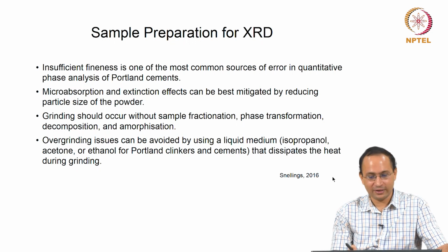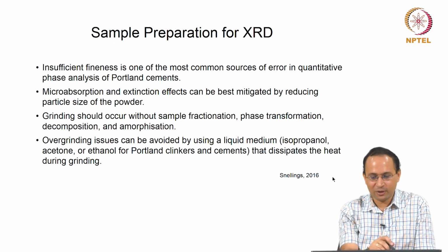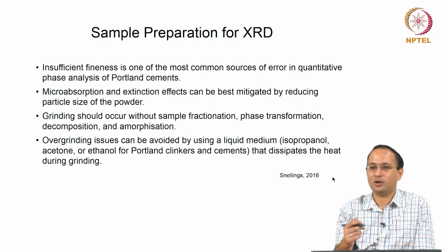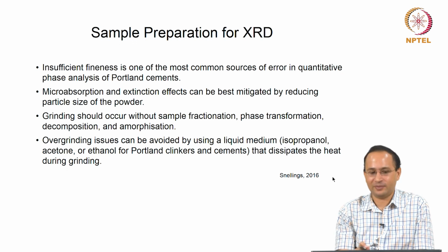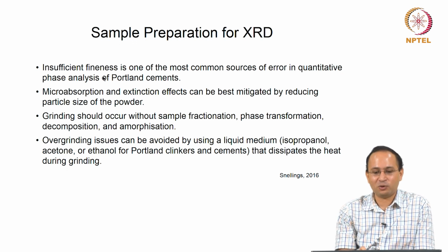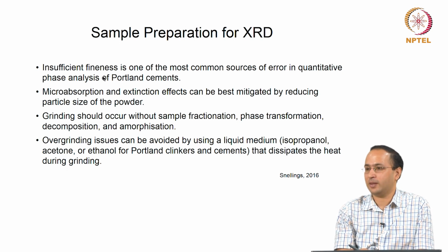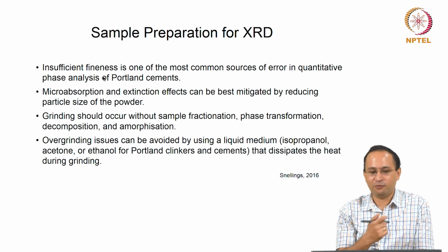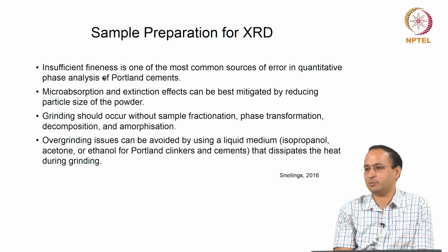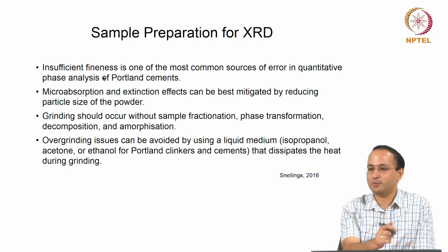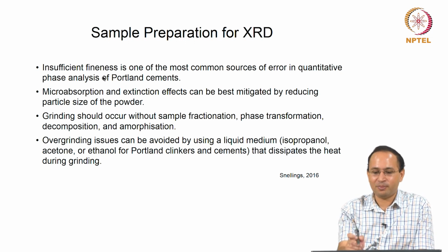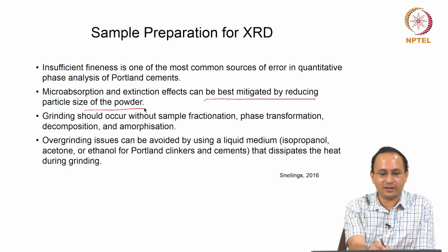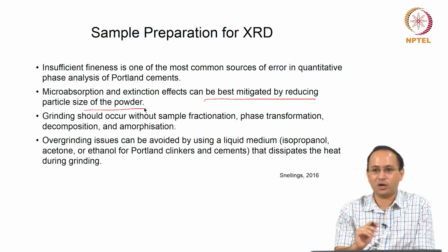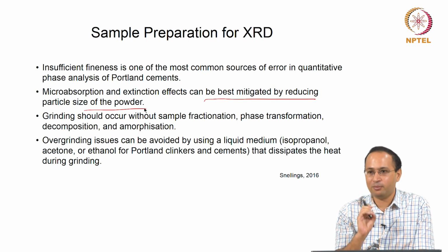As we saw in the last lecture, there are a lot of issues we can resolve when you use fine powder. Insufficient fineness is one of the most common sources of error in quantitative phase analysis of Portland cement. If you want to do quantitative phase analysis and you have insufficient fineness, that will cause a problem. Microabsorption and extinction effects can be best mitigated by reducing the particle size of the powder. So, that is the key, you have to make sure you are using fine powder.